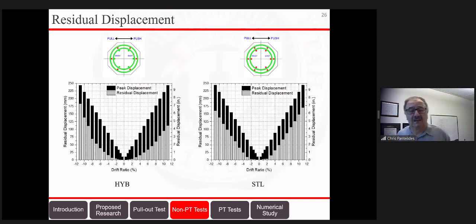So for example, for design, as I mentioned, we're interested at 3% drift. So if we go all the way down to 3% drift, the hybrid had a residual displacement of only 9 millimeters, whereas the steel had 13 millimeters. So it's a little higher. And then at 6% drift, the residual of the hybrid was 37 millimeters. That's down here. And then the steel had a residual of 65 millimeters, so almost double. Now for reference, most codes consider 1% residual as the limit to being serviceable. So here 1% means 22 millimeters. So if I drew a line at 22 millimeters, you'd see that the hybrid actually performed better than the steel.